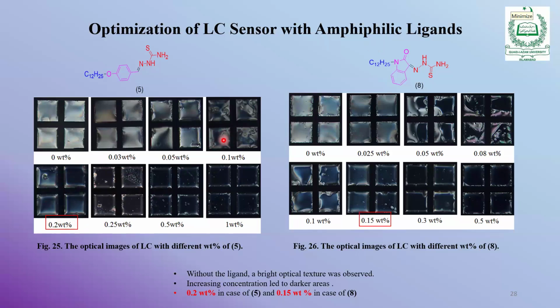So the liquid crystal here is showing its alignment, right. But here you see the liquid crystal is not showing anything. What this means is that when you will add some foreign object and it interacts at the liquid crystal interface, aqueous interface, it will show its signal. So if it interacts, it will change this thing, and if it will not interact, it will remain dark.